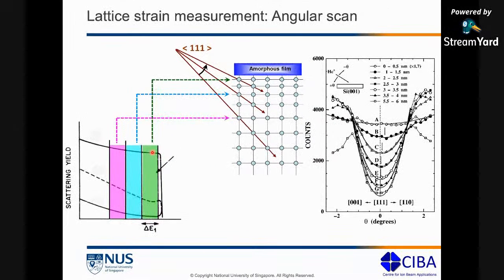Then we collect the counts from each of these regions and plot them against the tilt axis, the tilt we gave to the crystal. Once we do that, we get these sets of curves, which are called angular scan curves or rocking curves. So what do these curves mean? If you look at this bottommost curve, curve G, the lowest point has the lowest backscattered counts compared to all the curves, which means the channeling at this point is really good. That means this curve corresponds to this part of your sample where the crystalline structure is good and the channeling is good.